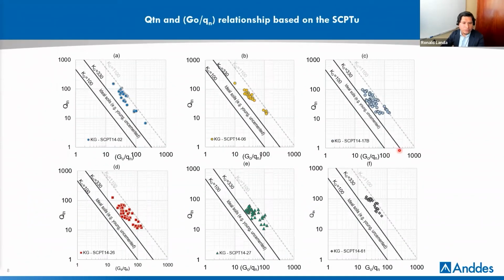So here are some charts that depict the calculations made for KG for these 6 SCPTs we have picked. And well, we outlined the key aspects that induce an increase in the CRR. Microstructure goes with the soil, and there is an increase in the CRR by cementation. It is no longer an ideal soil. So there is cementation between particles forming microstructure along the ore at small strains. It's now an index of soil response at large strains. And it can be proposed in a methodology that includes the calculation of this normalized index to quantitatively assess the microstructure effects.